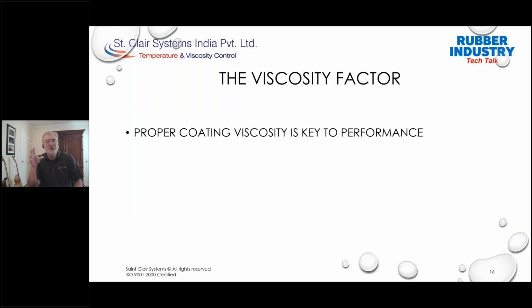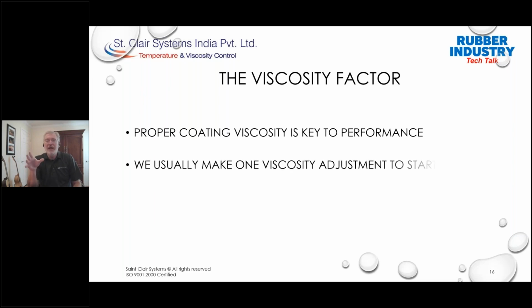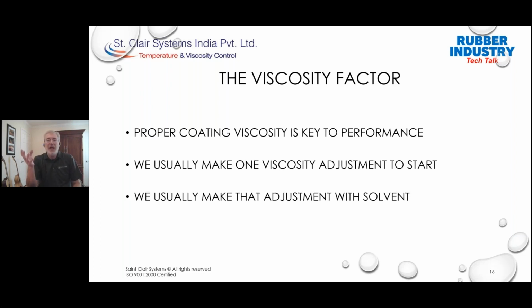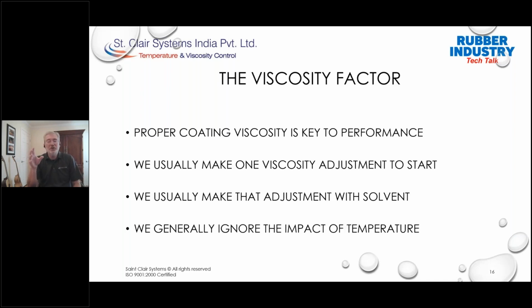It's important to understand the impact of viscosity in our process. Proper coating viscosity is key to successful product outcomes. Yet, even in today's modern applications, we usually make one viscosity adjustment and it comes at the beginning of the process. And we usually make that adjustment by adding solvent. And we generally ignore the impact of temperature on our process outcomes.